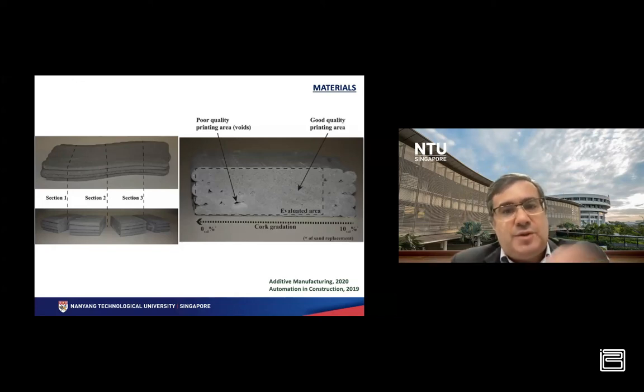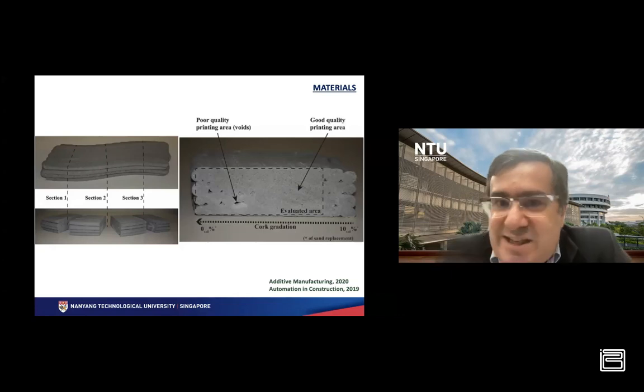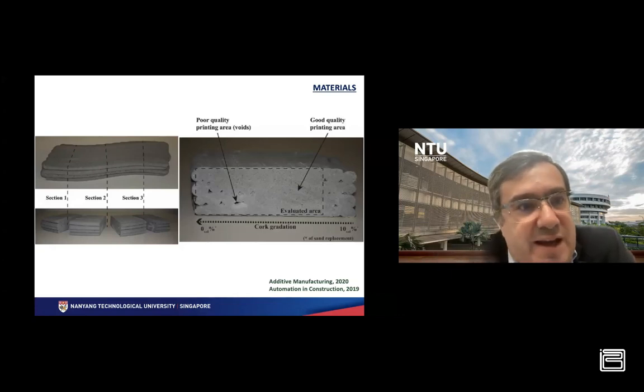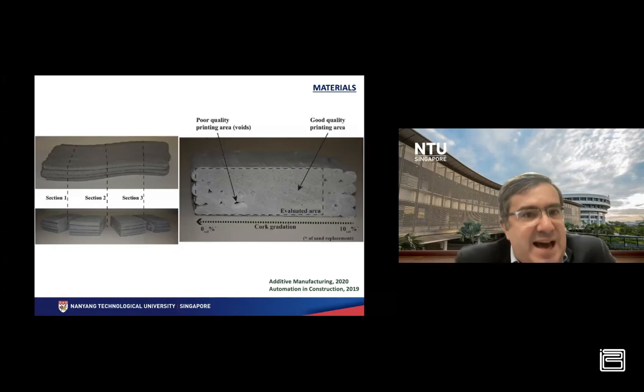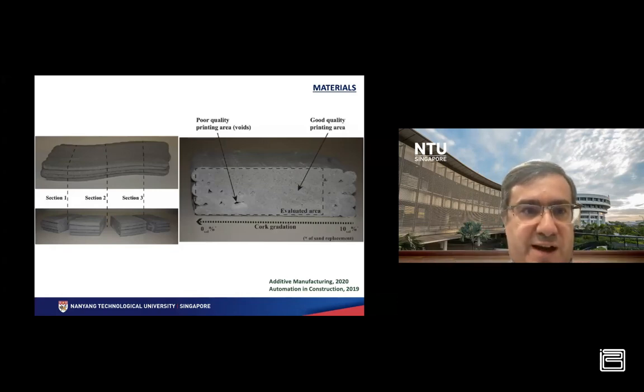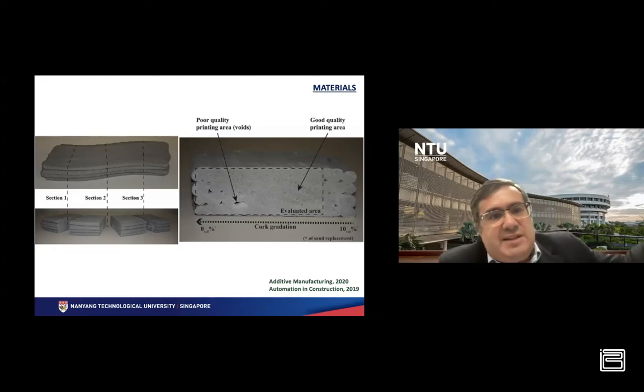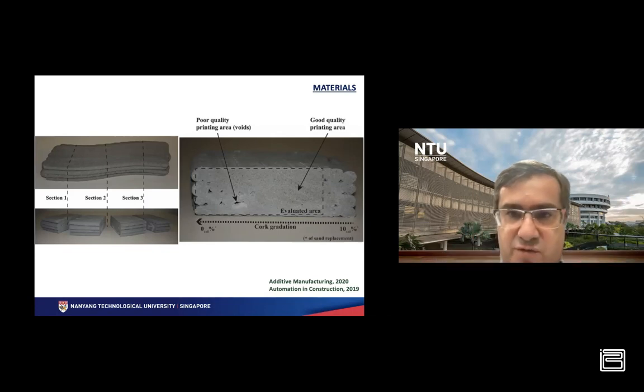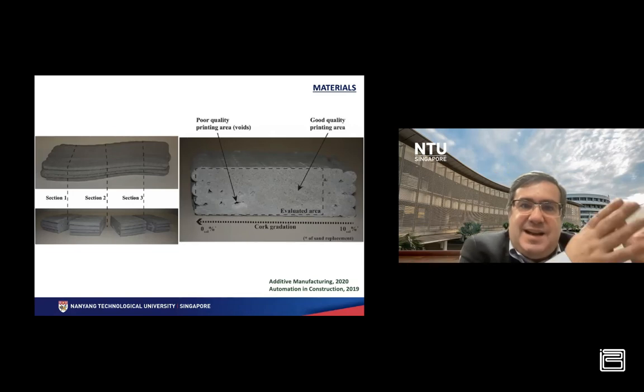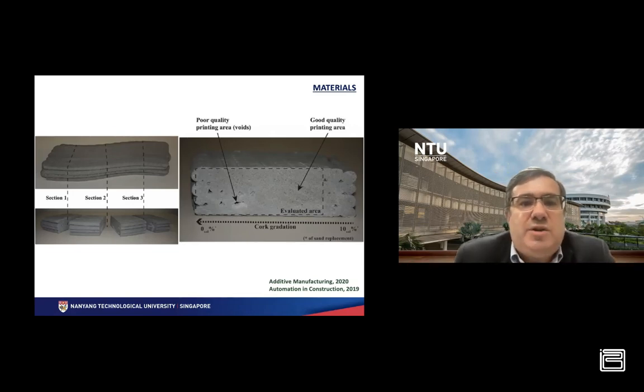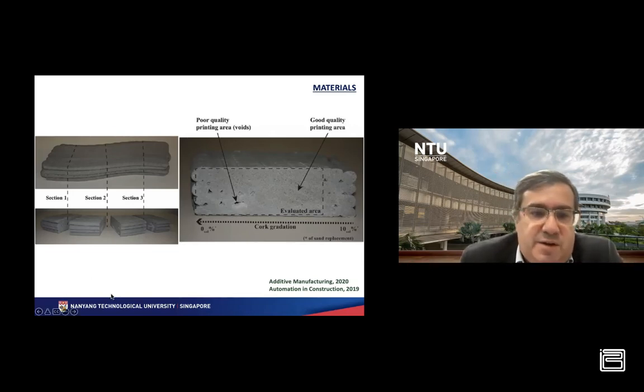But we are trying to design these printing materials in a proper way, because the materials for extrusion-based process must present a shear thinning behavior, which means that the viscosity decreases by increasing the strain rate. And this is always the starting point when we develop new materials for concrete printing.